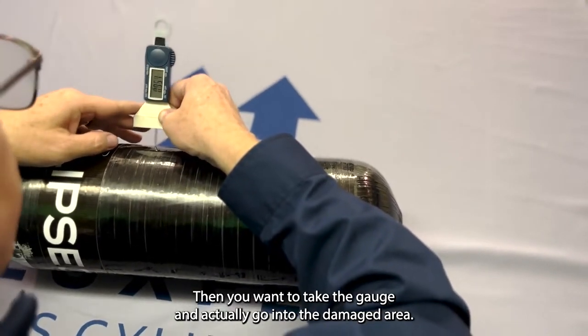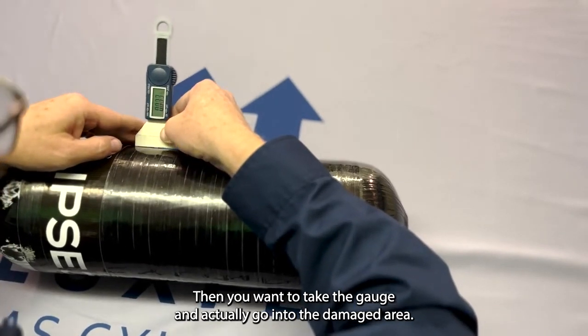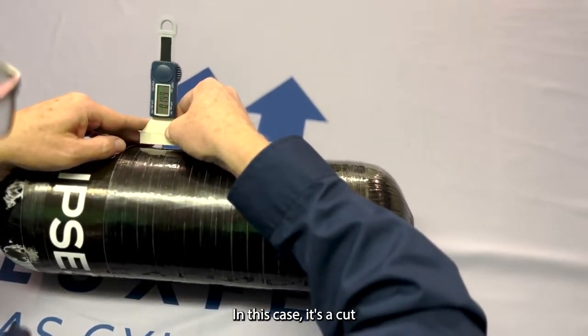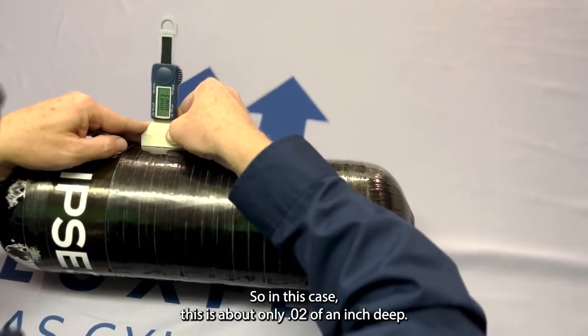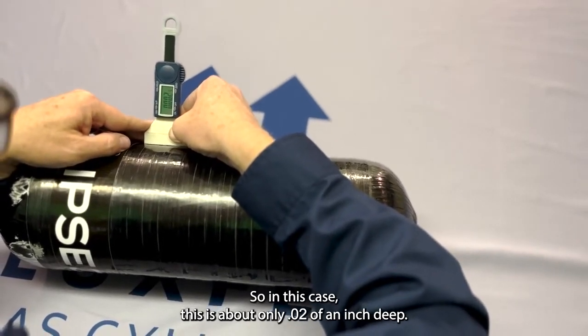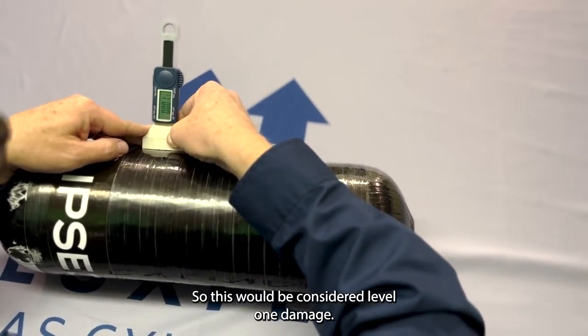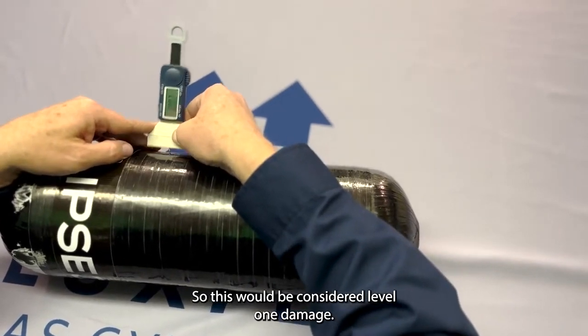Then you want to take the gauge and actually go into the damaged area. In this case, it's a cut. And you want to take a reading. So in this case, this is only about 0.02 of an inch deep. So this would be considered level 1 damage.